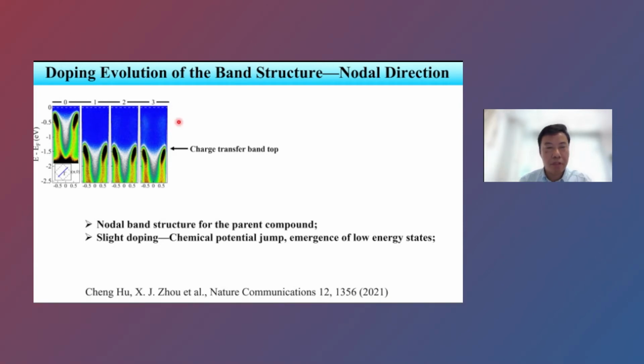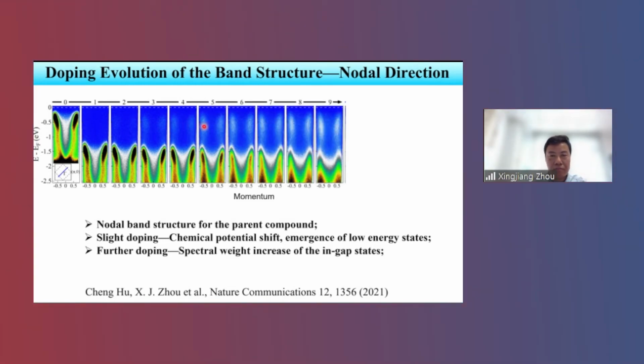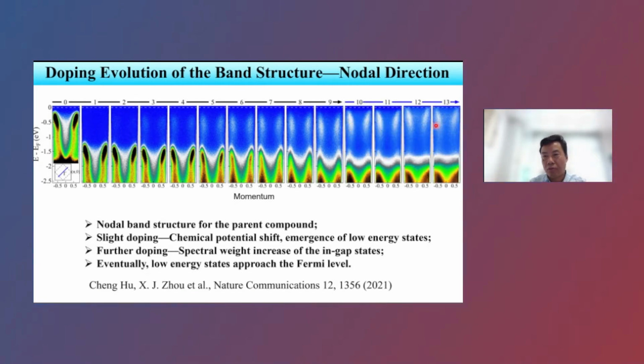This is a good chance, because this is a gap region. ARPES usually cannot see the gap above the chemical potential because the Fermi function is cut off. But by doping electrons, now we can expose a large area of the gap here, and we can see something start to emerge in the gapped area. With further increase of the doping, you can see that the in-gap states get stronger and stronger, but they are still away from the Fermi level. They do not reach the Fermi level. Eventually, when the doping level reaches about 12%, 0.12, these nodal states reach the Fermi level. This is basically along the nodal direction. We can see how the low energy electron states appear and evolve with the doping.